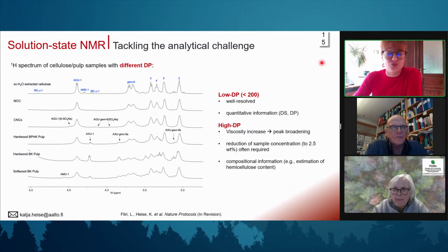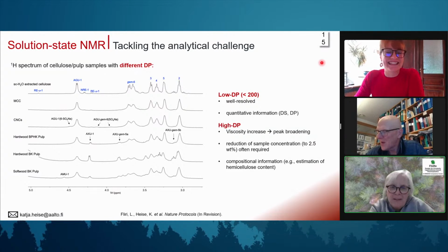You could potentially use 2D NMR methods like HSQC or HMBC, but it really depends on the signal assignment: where your signals are, how well they are resolved, and how complex the modification and the derivative that you get are. This is also why we very often use model compounds, because then you can clearly compare the signals from the model compound and from the cellulose, especially with lignocellulosic pulps, where the complexity of the NMR spectrum gets even larger. It's sometimes really challenging to properly assign signals. I don't know if this answers your question, but it is really challenging. It's a very nice method for molecular analysis, but you definitely need someone who really knows what he's doing when assigning signals from NMR spectra.